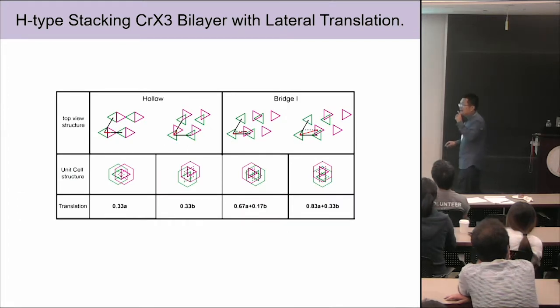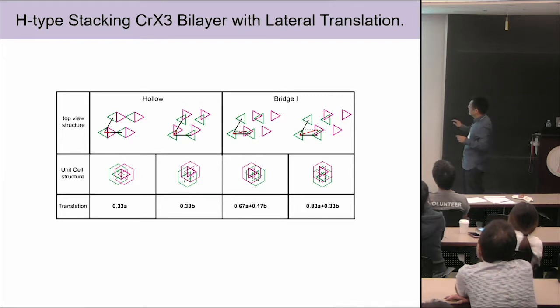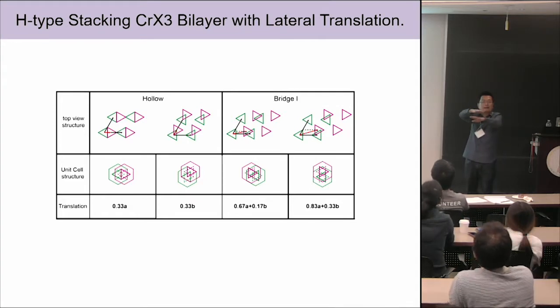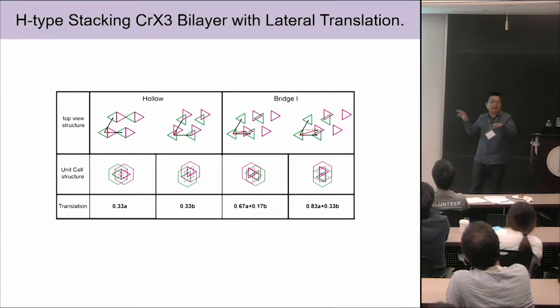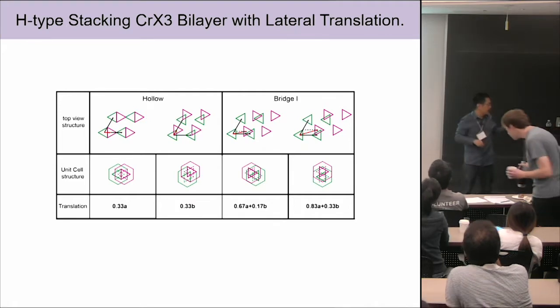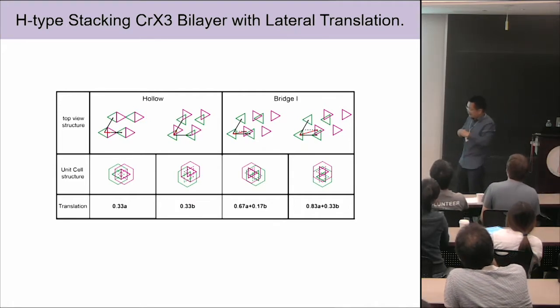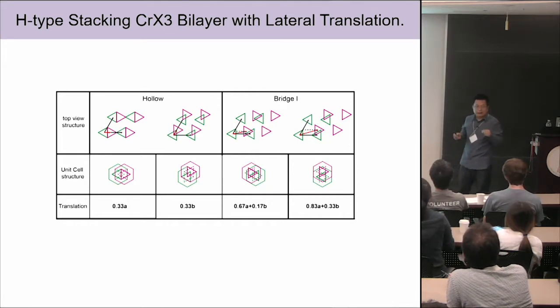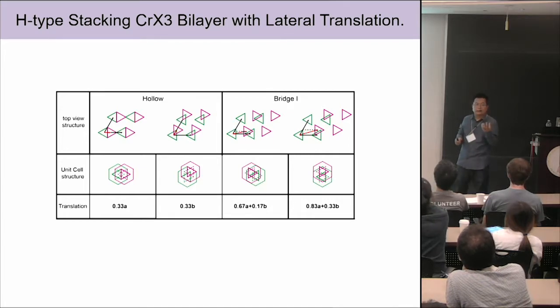There's another type of stacking called H-type stacking, which nobody had discussed before. In R-stacking, the top and bottom three atoms of a single layer have 180-degree rotation. For H-stacking, they don't. All X-ray diffraction data says this crystal should be in R-stacking — no H-stacking. But there's another mystery: chromium tribromide, which is the same class of chromium trihalide with only the halogen changed, is a ferromagnetic insulator. In the same class, why is one antiferromagnetic and the other ferromagnetic? It must have something to do with the stacking.